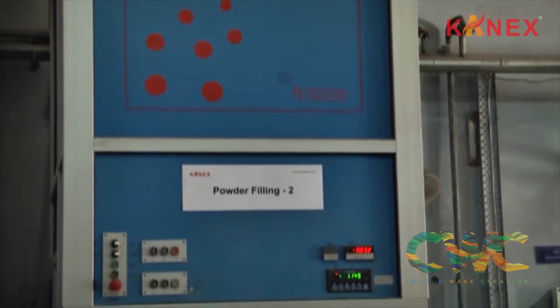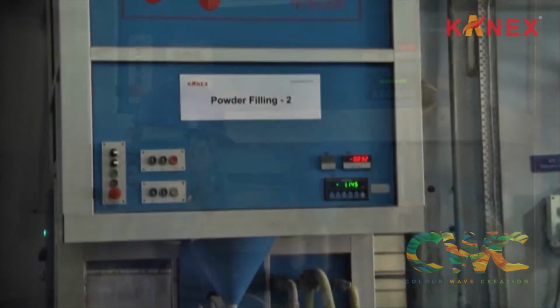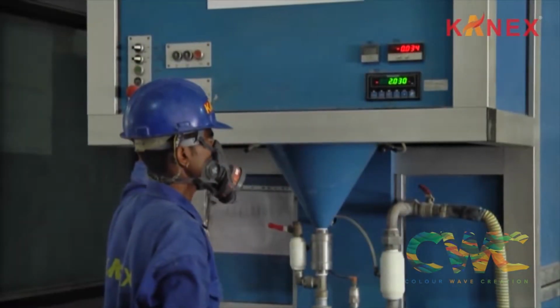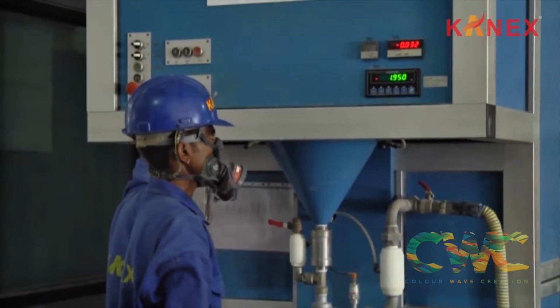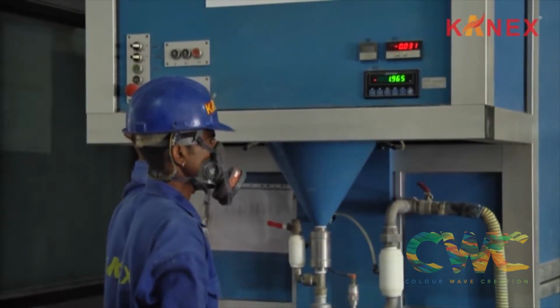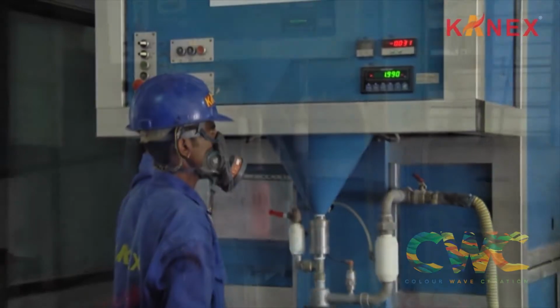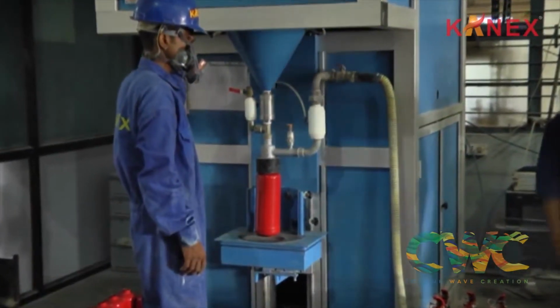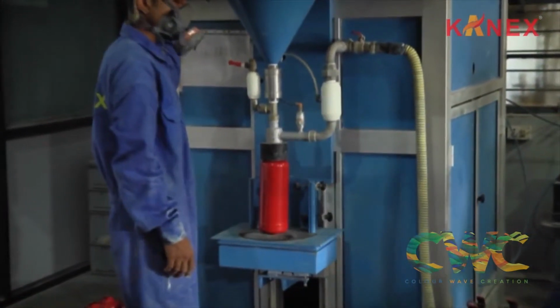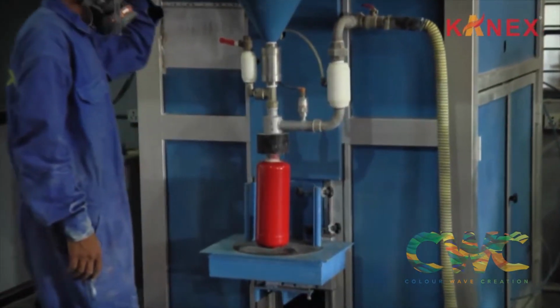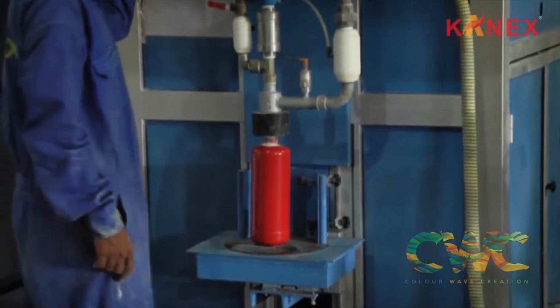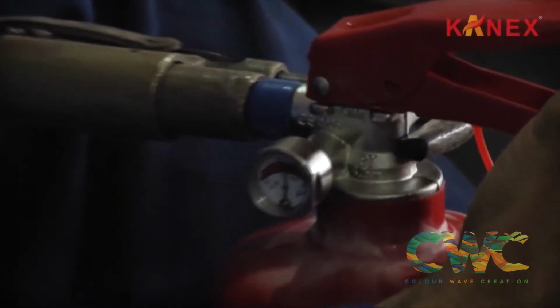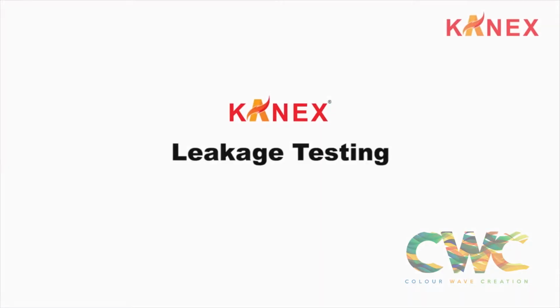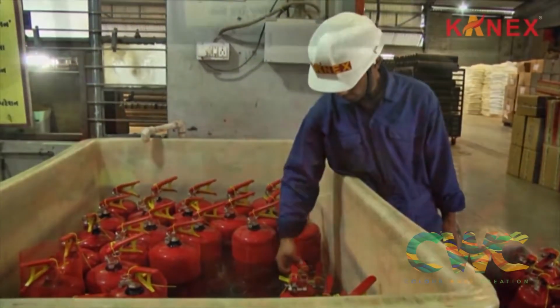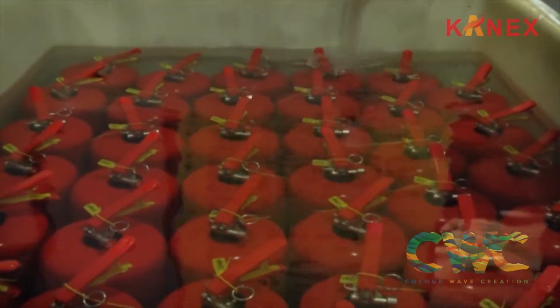quality of powder coating. Kanex has an automatic German-make powder filling machine which has a filling tolerance of plus or minus 2% and filling accuracy beyond the requirements of IS and EN3 standards. It also has the capacity to fill 800 cylinders in 8 hours and also has automated nitrogen filling stations for precise filling. The extinguishers are subjected to a leakage test in a water tank by immersion and applying soap solution.